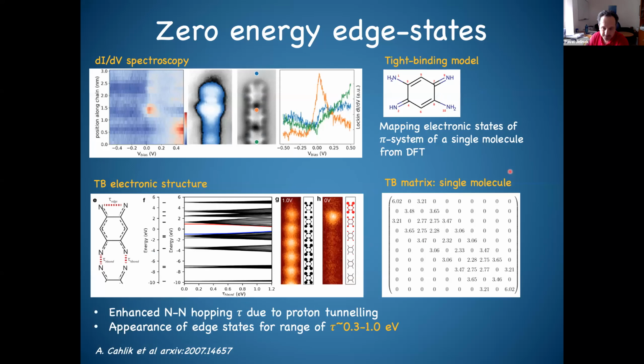So what we opt for here is to look at a tight binding model. I told you that we suppose this hydrogen is the only weak coupling in the tight binding, but now because we have this proton tunneling, probably this coupling is enlarged. So what we do here is use a tight binding model of the single molecule, and now we turn on the hoppings which represent this proton tunneling, so this N-H...N bond. And now if you tune these parameters, to something like 0.3 or 1 eV, you can tune the system so that you see this edge state. But I have to remind you, this is not a topological edge state. This is an edge state which comes from renormalization of this site due to this hopping here.